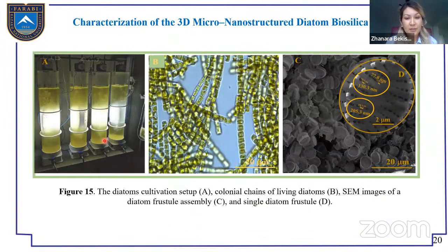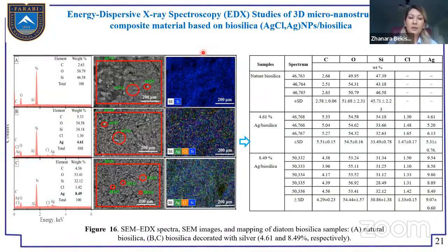Here are the diatom cultivation and the light microscopy of the living diatoms, and the scanning electron microscopy study after purification of the diatom biosilica, with pores, nanopores. The spectral analysis of the SEM images and the mapping of the obtained nanocomposites with different concentrations, where the initial concentration was 5 and 10%. The adsorbed silver was equal to 4.61 and 8.49, and we can see the distribution of the pure silica and after modification with silver and chlorine ions on the mapping.